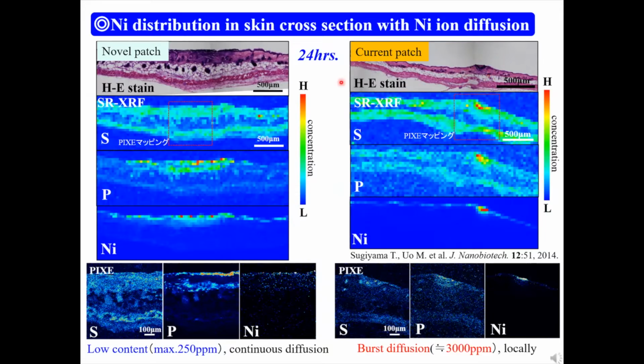In contrast, with the novel nanoball patch, the nickel ion content was not so high, but it was continuously supplied from the suspension. Then, the nickel ion diffused into the skin gradually. Then, the skin was not damaged by the nickel absorption. Therefore, the metal nanoball would be a novel metal allergy patch test resource.